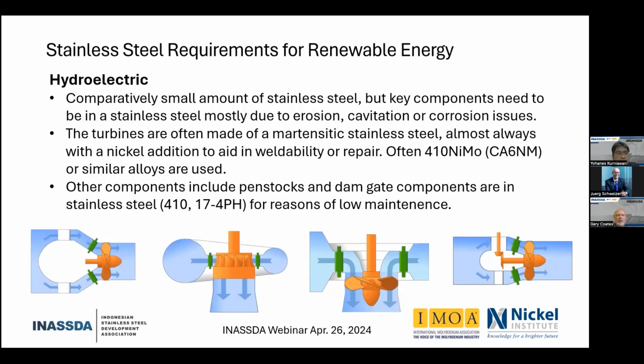Here's where that 17-4 PH, which doesn't require a quench afterwards and therefore has low distortion, is used for certain components where you have long lengths. They might be 50, 70 meters in length, and you want them perfectly flat, and the rollers of the dam gate will go against it. And you want low maintenance in those applications.